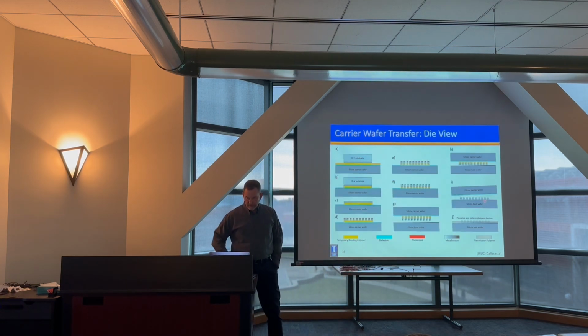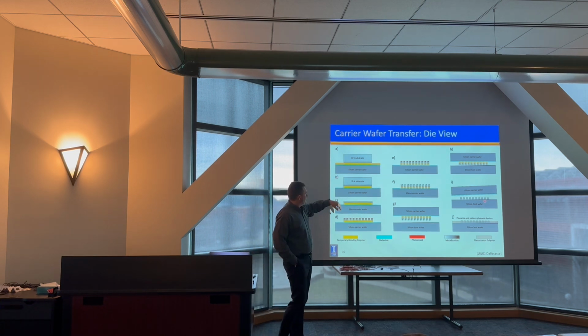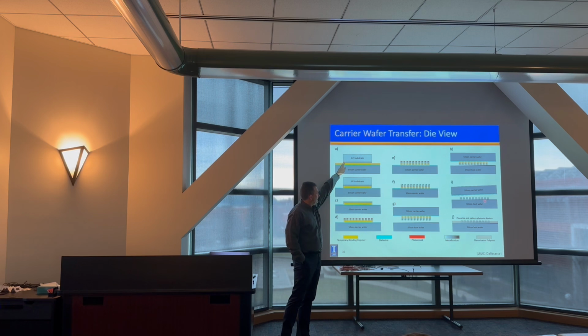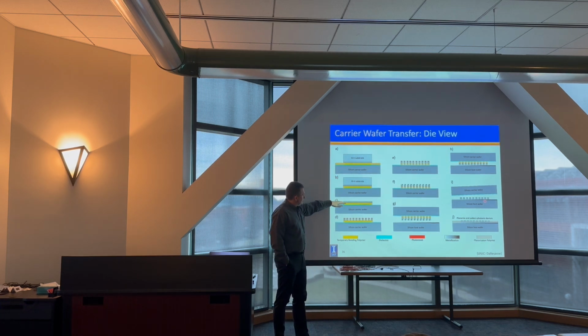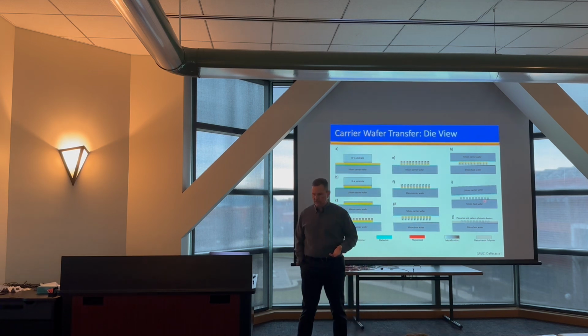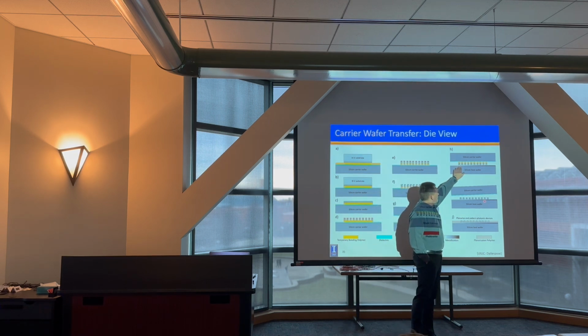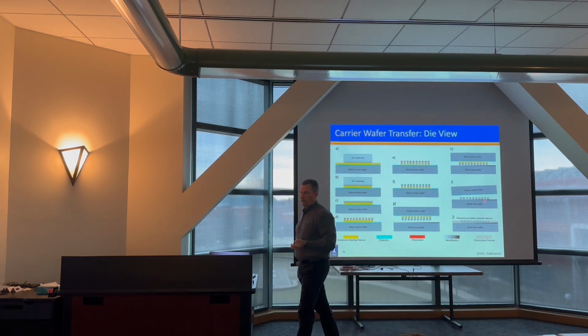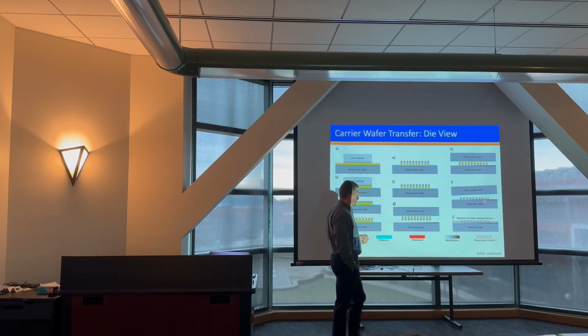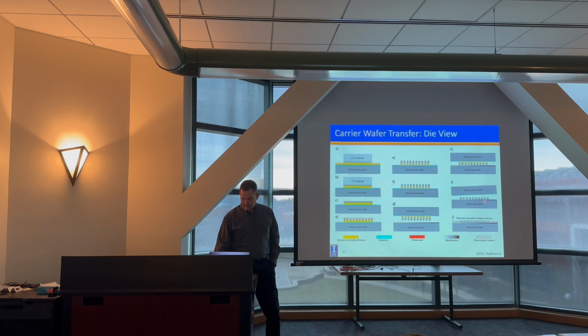Okay. If we imagine what that looks like on a cross-sectional basis, we have our silicon carrier wafer. This is our 3-5 epi side down. We remove the substrate. We do dry etching to precisely pattern where the 3-5 material is located. We then deposit a bonding material onto that. This is a temporary bond, by the way. We carry that through, we flip it over. On our silicon host wafer, we have receptor sites that we've metallized using a different metal. And then we do a permanent bond between those, release our temporary bond, and we end up with 3-5 islands precisely located on our silicon host wafer using this epitaxial transfer process. Now there's some particulars to that.